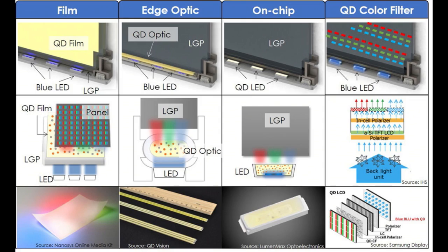And by far the vast majority, and this is the case for, I believe, all of Samsung's TVs, is in the film column there, that first one. So the majority of TVs that contain quantum dots have a film of quantum dots in them. And so behind the screen, you have basically a plastic sheet that's embedded with quantum dots, and a blue LED either on the edge or behind the screen, and those illuminate the quantum dots to give you your 3 colors. And then you have your typical color filter after that to isolate each independent color.